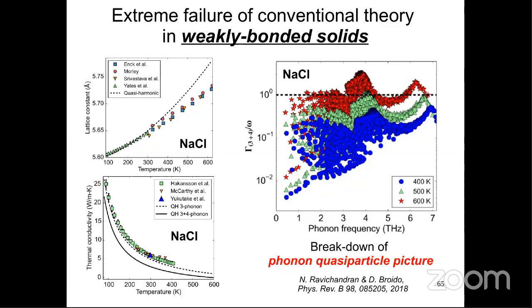That was a good question. So yeah, right. If you take a very thin material sample, for example, you will have boundary scattering. So this 4-phonon scattering can be treated on the same, quote-unquote, footing as 3-phonon scattering, in the sense that you can calculate an effective mean free path combining both 3-phonon and 4-phonon scattering rates. And if that mean free path is comparable to your system dimension, then diffusive scattering at the boundary becomes important. So it's really a comparison between the length scale of your sample, temperature as another variable, and the material that you are using.